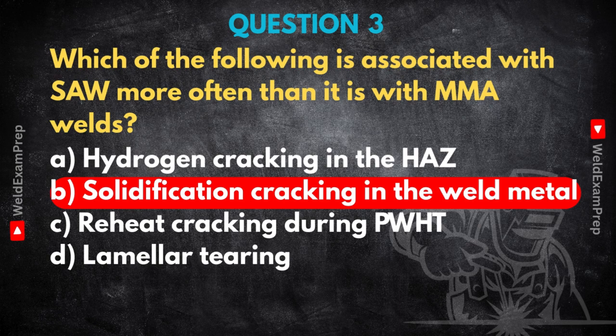I remember a project quite early in my career, actually, heavy plate, lots of SAW. We kept seeing these tiny micro cracks in destructive tests. The first thought was maybe hydrogen. But knowing SAW's characteristics, that deep pool, we pushed to check for solidification issues. And sure enough, material analysis showed sulfur levels were just creeping up at the high end of acceptable, enough to cause trouble with that specific procedure. That was a real aha moment for me. It drove home that this process-specific knowledge isn't just academic, it's a powerful diagnostic tool. It helps you target your inspection efforts where they're needed most, helps prevent costly rework or much worse. Yeah, being proactive rather than just reactive.